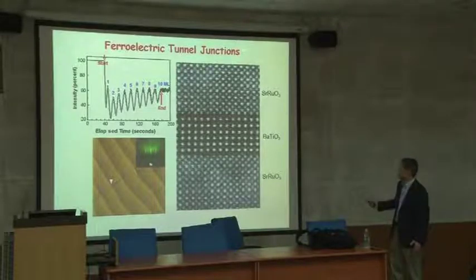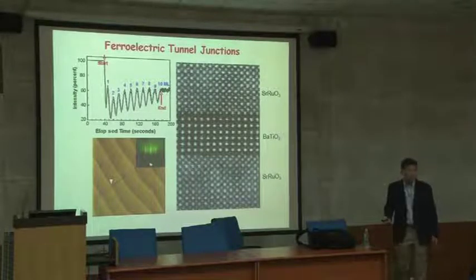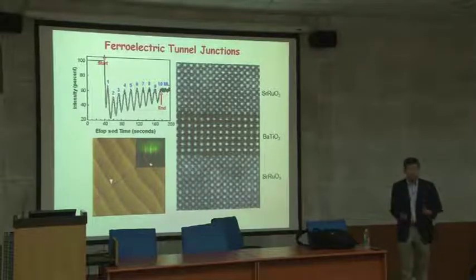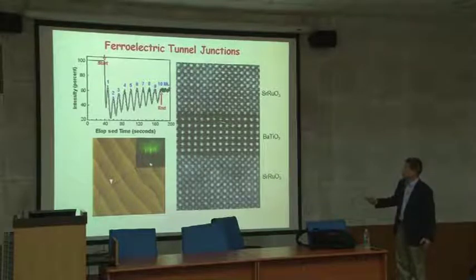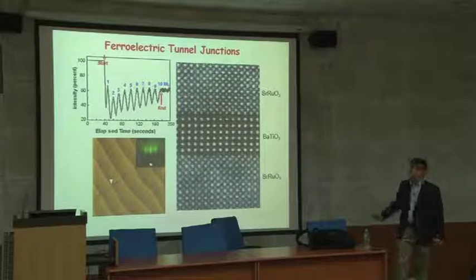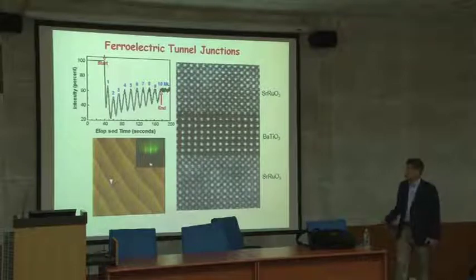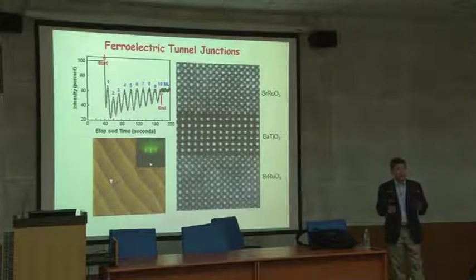And another example is ferroelectric tunnel junctions. Strontium ruthenate, barium titanate, and strontium titanate, and strontium ruthenate. And there's a metallic layer so that you can apply an electric field. You can switch it. But you can see that the barium titanate layer is extremely flat. And then you can count how many barium titanate layers, by counting how many oscillations. After going through all the layers, the surface is atomically flat like this. So this is the level of epitaxial thin film growth.